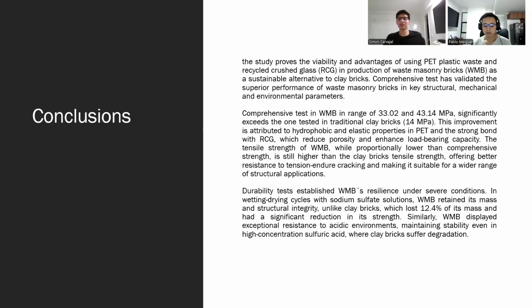In compressive tests, WMBs range from 33 to 43 MPa, significantly exceeding the one of the traditional clay bricks, that is 14 MPa. This improvement can be attributed to the hydrophobic and elastic properties in PET and the strong bond with the RCG, which reduce porosity and enhance load bearing capacity.